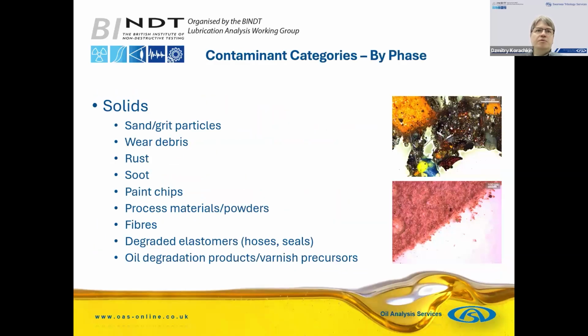So if we split the contaminants by phase, one of the main phases is the solids. So we have sand and grit particles, wear debris generated within the machine, but it becomes a contaminant immediately after that and can cause further wear. Things like rust, soot in engine oils, paint chips coming off the different surfaces within the equipment, maybe the painted surface of a tank.